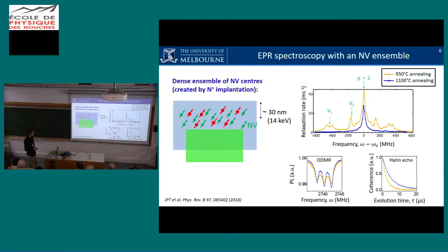So it's actually even shorter if you take a naive model. It's actually a complex physics of the interaction with all P1 and all those vacancies that detune each P1 essentially. So they don't interact as much because you have the dynamic range. So you would expect actually longer if it was just P1. But it's work in progress to actually model that completely. So we think we are anyway limited by all impurities, vacancies, vacancy chains, and also P1s, and altogether those limit the T2. P1 density, so we implant here 10 to the 13 per centimeter square at 14 keV in that particular sample.